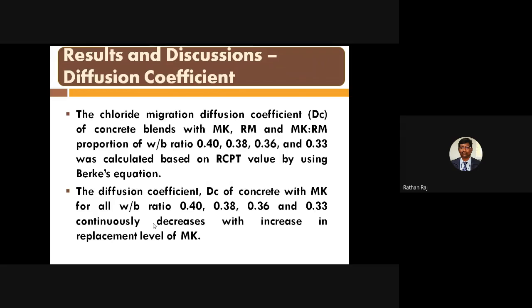So now I want to discuss with you a few results very fast, based on these two methods, diffusion coefficient and the chloride resistance. Here I used metakaolin as one supplementary cementitious material separately, red mud as a supplementary cementitious material, and the combination of metakaolin and red mud in different proportions like 50:50 ratio, 60:40, 70:30, and